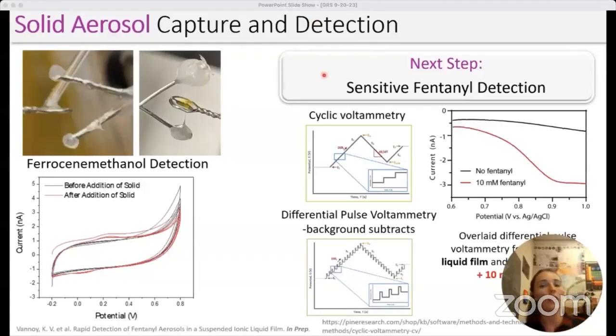But still, all we're looking for is a current peak to act as our binary signal. In this DPV, you can see that when we have our ionic liquid suspended film and we put 10 millimolar fentanyl in it, we can observe a peak around 0.9 volts. And of course, in the background, we do not see that peak. While 10 millimolar fentanyl might seem like a pretty high concentration, this volume actually corresponds to the capture of about 17 micrograms of fentanyl. Right now we're pursuing the detection of actually aerosolized fentanyl powder, but obviously this needs to be done with a lot of care, and so we're still very carefully working on that.